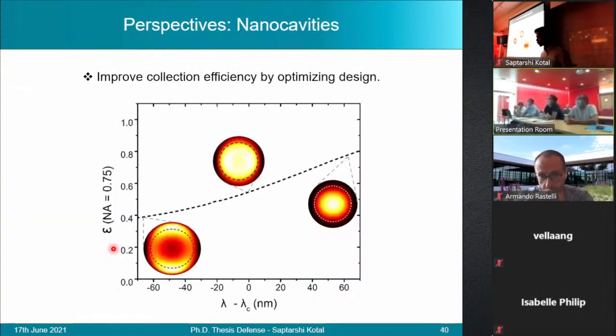Now, to go beyond what I could achieve during my PhD, we could improve the collection efficiency, which is currently limited by the divergence of the far field of our nanocavity. And as we can see already, given the current design, just by having an emitter which is strongly detuned in the positive direction, we expect to have a more directional output beam.